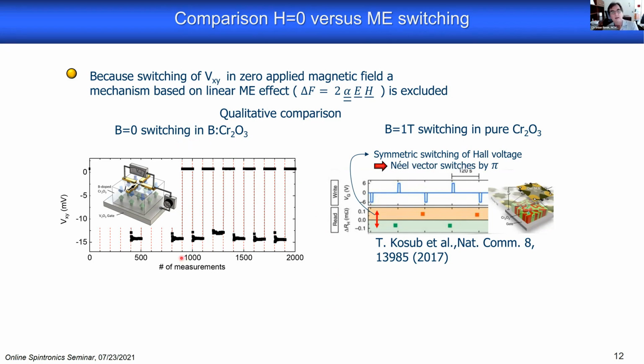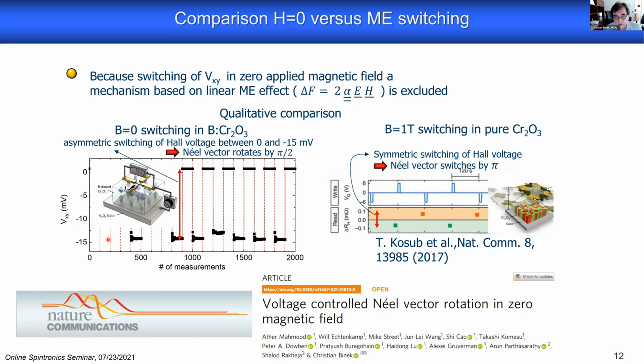Now, what happens in our system? Well, if one looks more closely, one sees a very obvious difference. We are not switching the Hall voltage, and therefore also not the Hall resistance, between symmetric values. We switch between a value that is almost 0 and a value that is non-zero. And this is already a clear indication that the states between which we switch are not just 180-degree degenerate. We think that is the clear fingerprint that this is a 90-degree switching, which makes the interpretation also much easier in the sense that if you would have to explain a switching of the remnant state and the remnant boundary magnetization by 180 degrees in the absence of a field that breaks time inversion symmetry, that's already a problem.